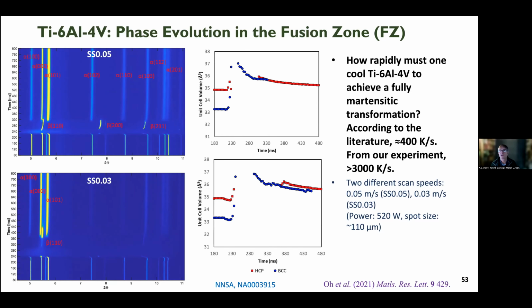One is if you freeze rather slowly, then you get a diffusional transformation, a civilian transformation, as some would call it. Whereas if you go very fast, you get a martensitic transformation, or so-called military transformation, where the constituent atoms don't have time to diffuse long distances, and so you get the sudden shears in the crystal structure, and it, if you like, flips over from BCC to hexagonal.